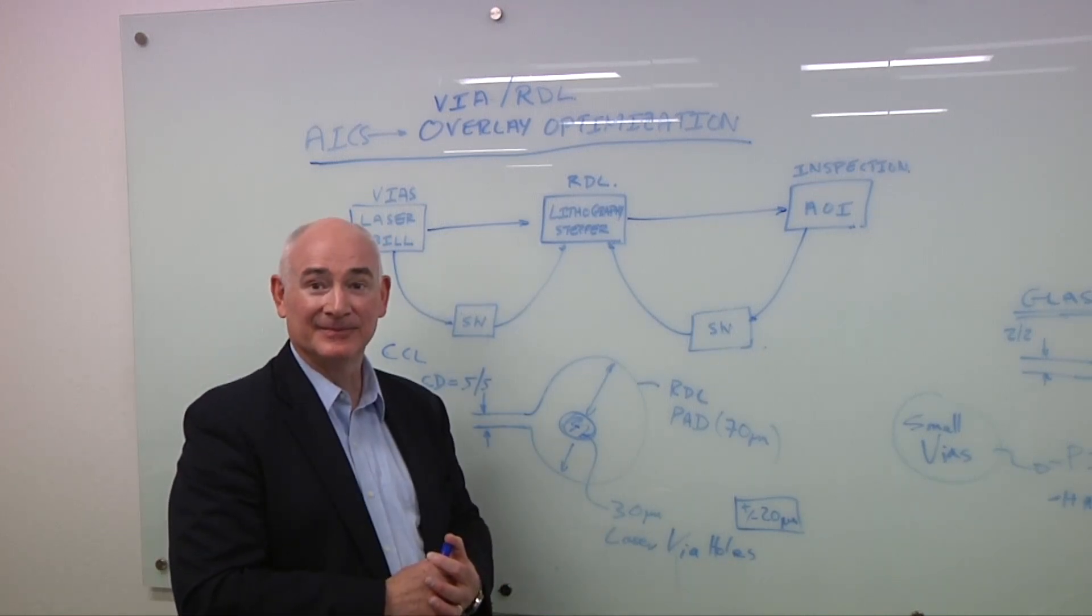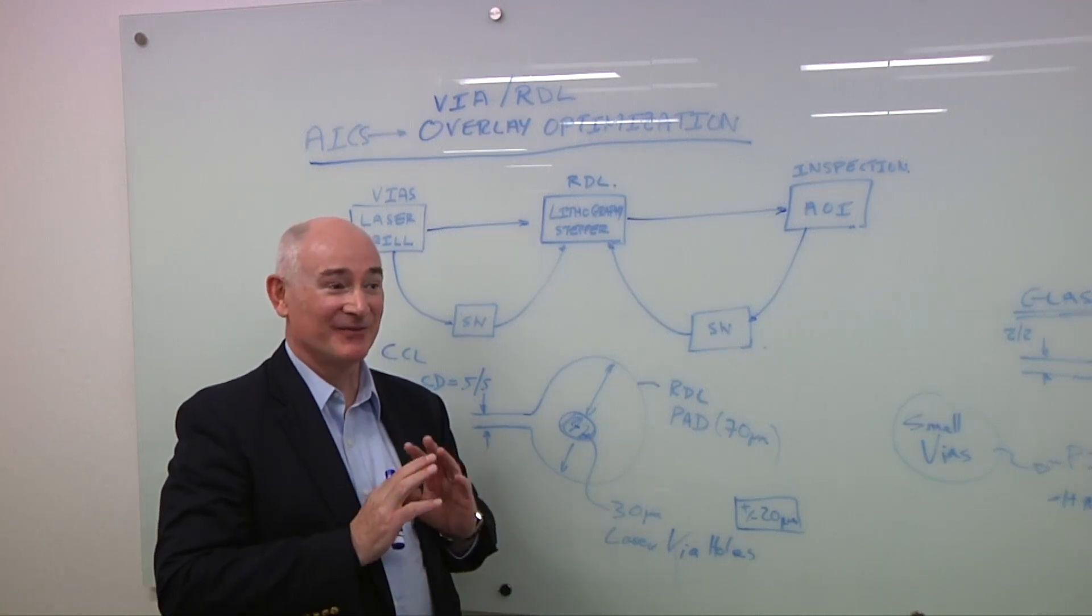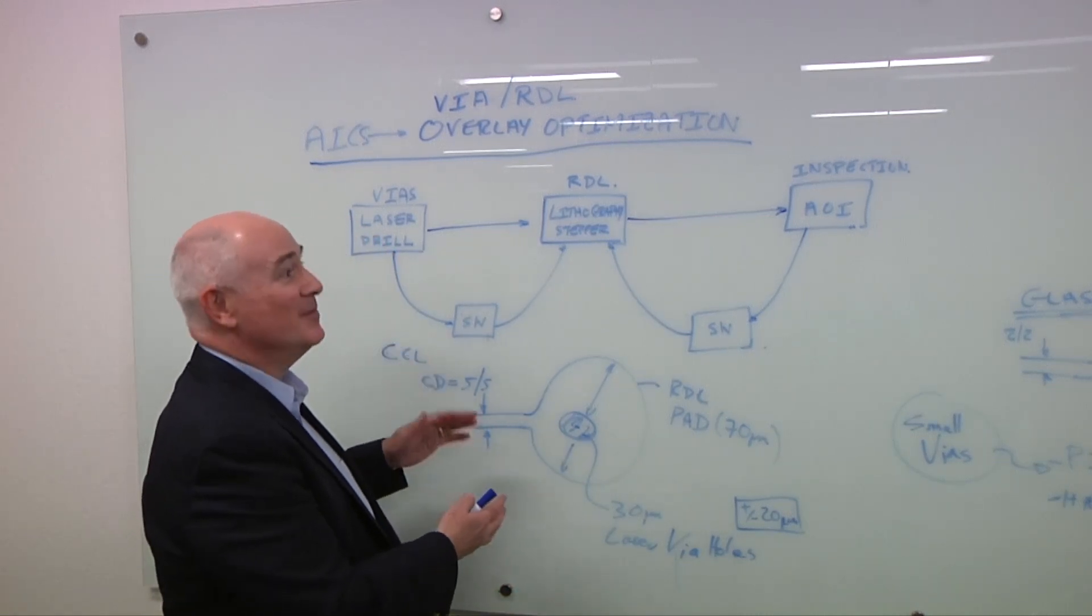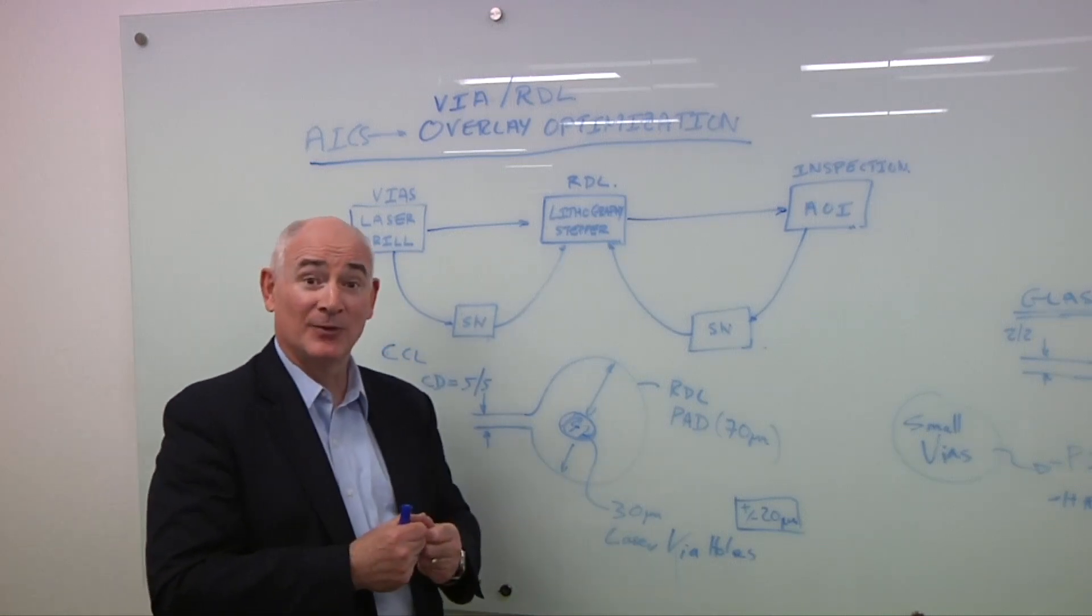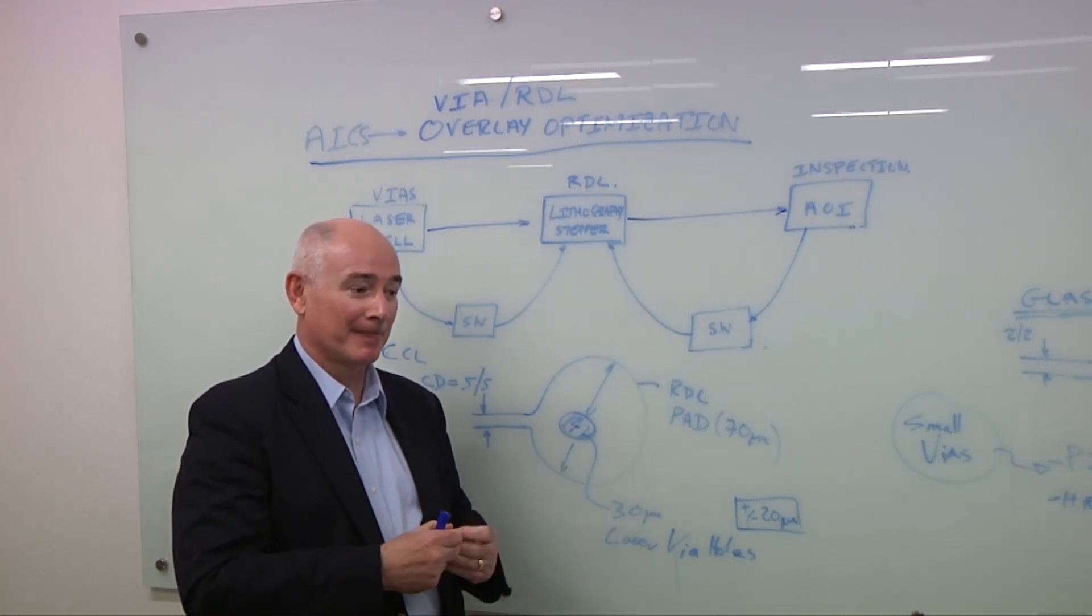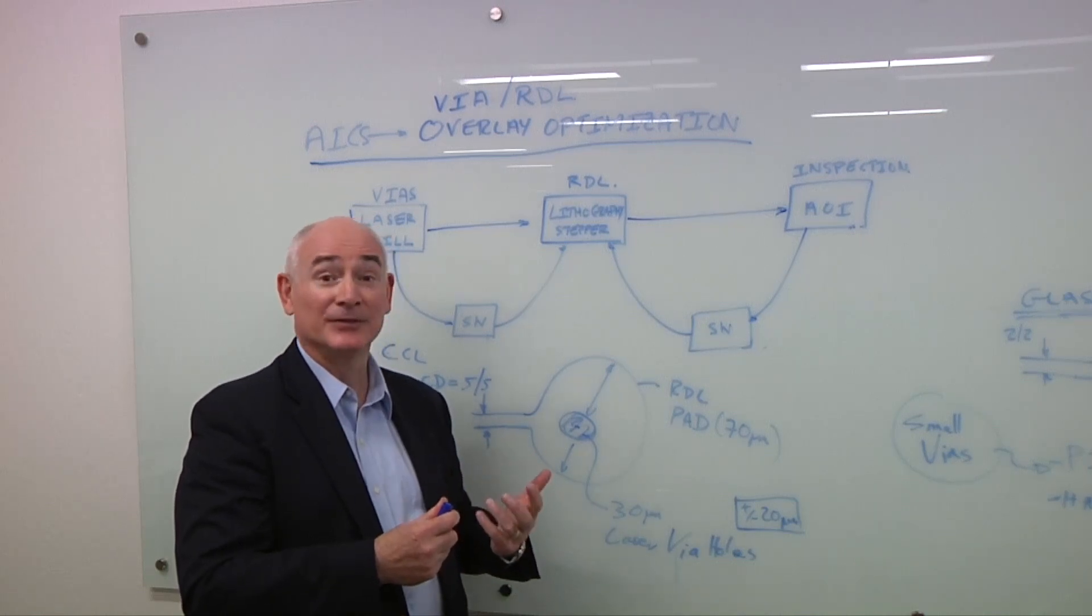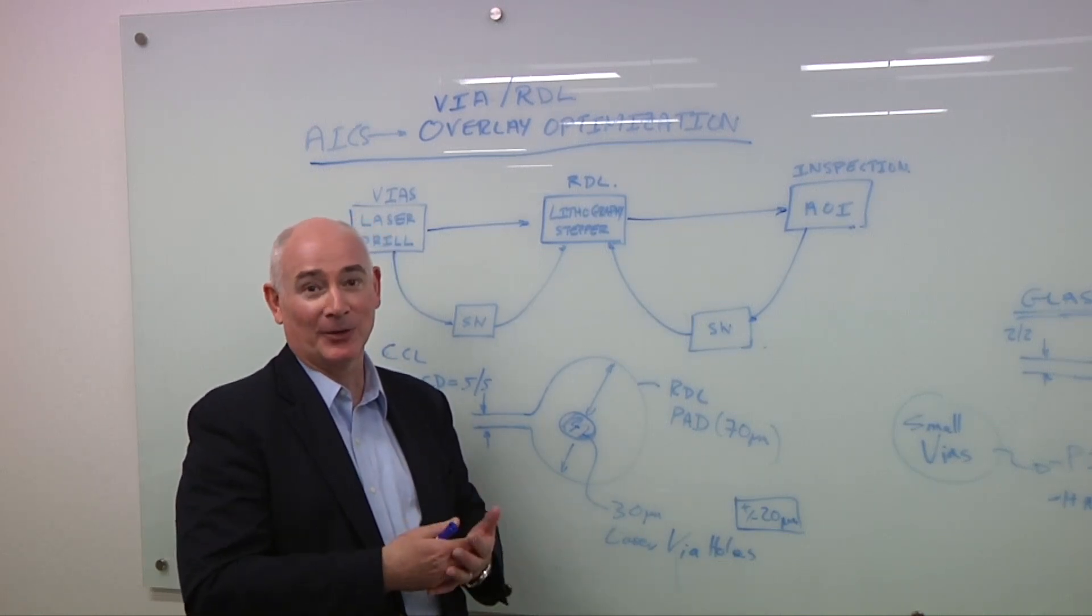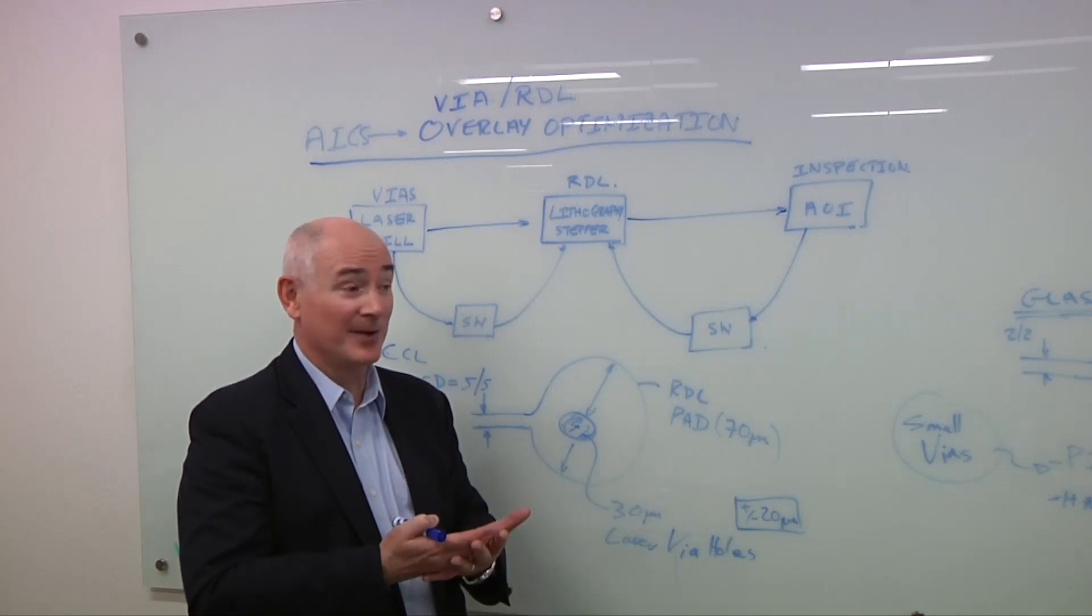What happens with glass? Yes, glass is what everybody's looking at right now because all the things I've talked about here are removed, effectively, because glass is very well behaved. As you heat it up and cool it down, it's got a very well understood coefficient for thermal expansion. It will not do the same thing that the copper clad laminate will because it's not built of the fibers.